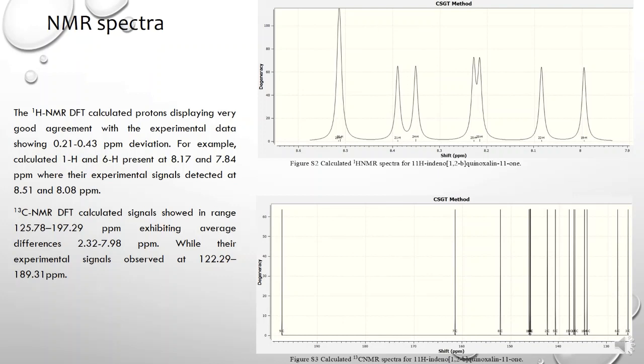For example, the calculated proton 1 and proton 6 are present at 8.17 and 7.84, while experimental show at 8.51 and 8.08. And the carbon 13 calculated shows in the range 125.78 to 197.29 with average difference 2.32 to 7.98, while the experimental is in the range 122.29 to 189.31.